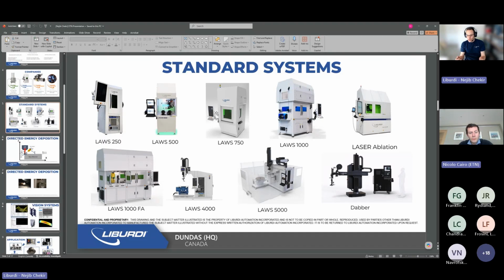That is a process that can take anywhere from 2 weeks to 4 weeks typically. Once you have these welding parameters, they're locked. So you qualify the process with a batch of representative parts. Sometimes a customer could tell us to weld 100 parts and ensure that 95 of them are good, for instance. And those 95 will go through destructive testing to ensure everything looks good in these parts. That would be one way to ensure that the weld looks good on the part itself.